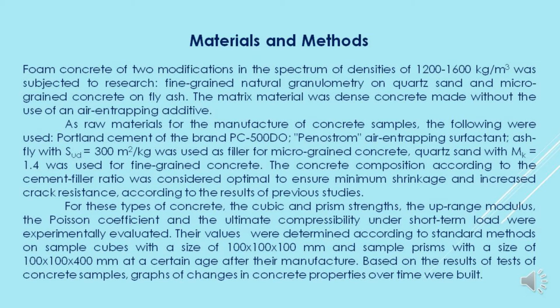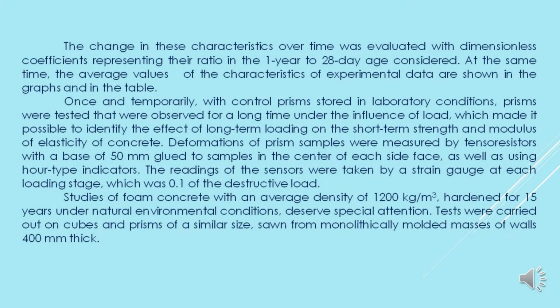Their values were determined according to the GOST methods on sample cubes with a size of 100x100x100 mm and sample prisms with a size of 100x100x400 mm at a certain age after their manufacture. Based on the results of tests of concrete samples, graphs of changes in concrete properties over time were built. Along with control prisms stored in laboratory conditions, prisms were tested that were observed for a long time under the influence of load, which made it possible to identify the effect of long-term loading on the short-term strength and modulus of elasticity of concrete.